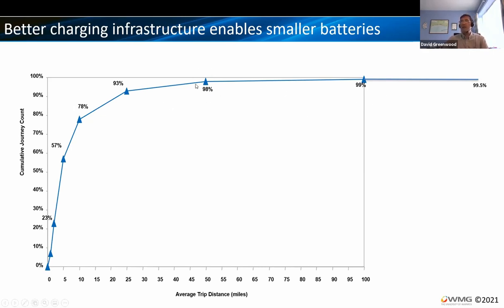So if I can capture 98% of journeys with a battery that's capable of doing 100 or 150 miles of real world range, so 2 or 3 50-mile trips in a day, the number of extra journeys I'd capture by doubling the size of that battery is remarkably low. And what you're going to start to see is as the charging infrastructure in the UK significantly improves, and particularly fast charging, the idea of carrying this 500-mile battery around with you is something that will become less and less the norm. And you'll start to see that batteries become smaller and faster charging.